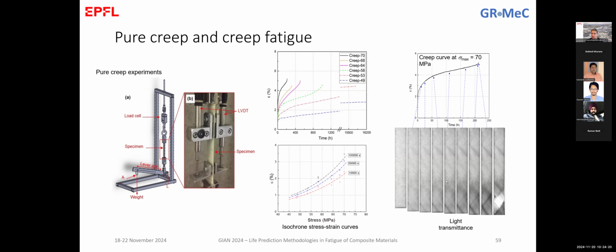And again, we've seen that there is damage in creep, but it is correlated mainly to the end of the creep test, which is probably what you know about this creep description. We call it the primary, the secondary, and the tertiary part of creep. And usually in the literature, people say that in the first two regions the material deforms, but any damage or deformation is recoverable, and damage is created in the material only at the end of the creep. In our case, we've seen some matrix cracks already in the beginning, and the main damage that led to failure is really attributed to the final stages of the creep.